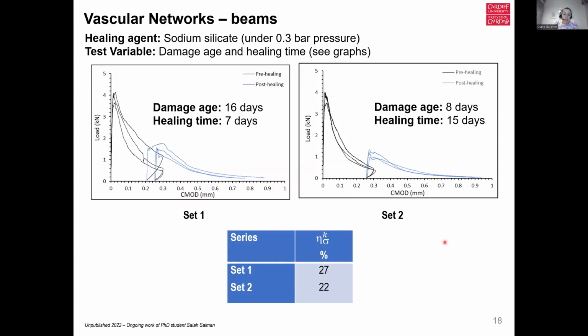What we do see though are very similar flexural strength recoveries, so that's 27% for the first set and 22% for the second set. And this really confirms what we see generally for our sodium silicate specimens, in that we tend to reach a ceiling value of about 30% for our flexural strength recovery.